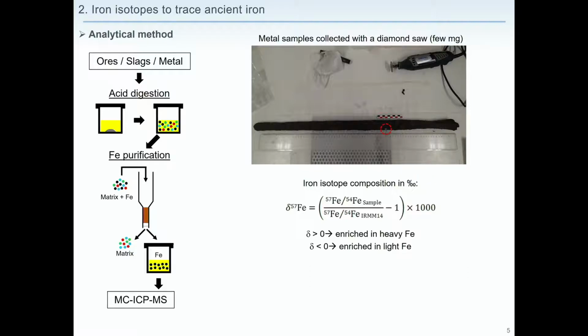Technically, ores and slag samples were crushed and powdered, whereas the metal samples were collected with a little diamond saw, as you can see here on this entire bar. We just need a few milligrams to make this kind of analysis. This is a major advantage of this method. It greatly limits the deterioration of the archaeological pieces.